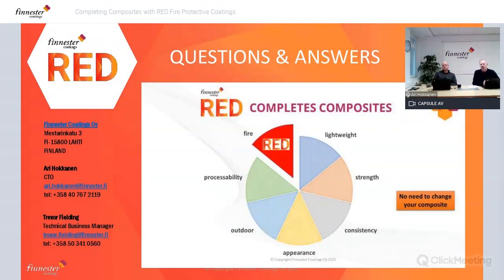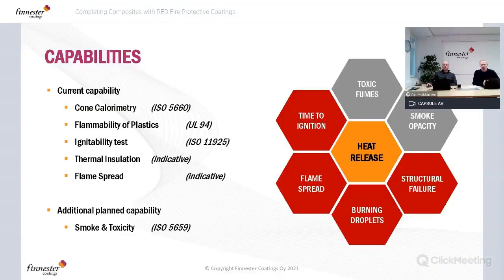So sometimes just 250 micron, 200 micron, depending on the coat, depending on what kind of properties you need. If you need only flame spread and time to ignition, one layer is enough. Burning droplets, 1 layer is enough. But then if you go to heat release and structural failure, you need 2 layers.